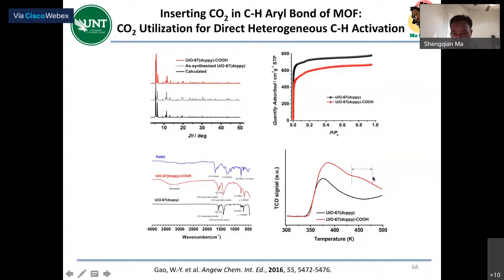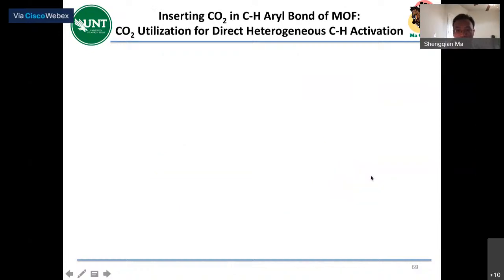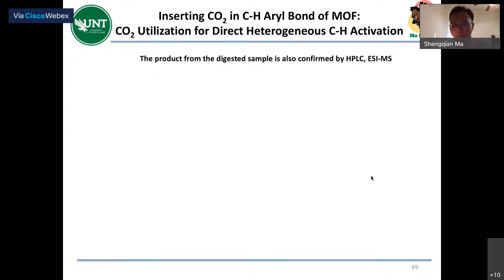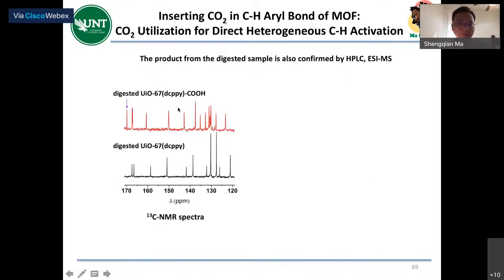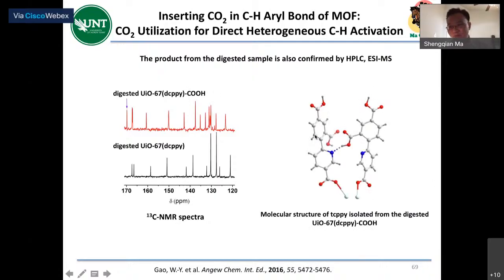TPD study. And also then we dissolve the MOF, digest it, and do the HPLC and also mass spec. We found there's this carbon-13, an additional peak from the carbon, from CO2 formed the carboxylate group. And also we can crystallize the ligand. You can see, right, this is the crystal structure. Okay, we digest the MOF after insertion of CO2. You can see the carboxylate formed from CO2 is here.